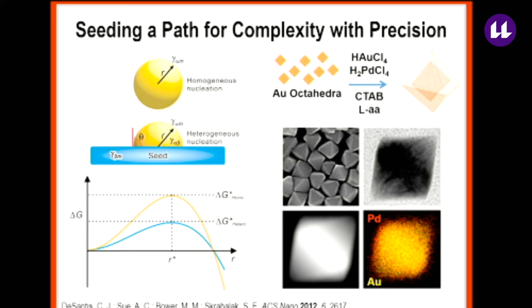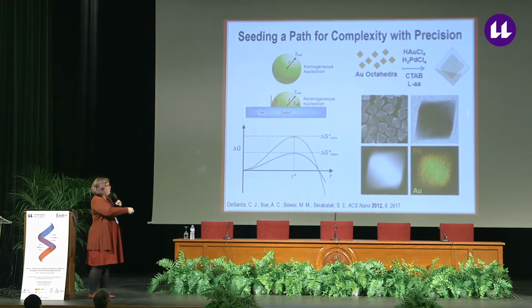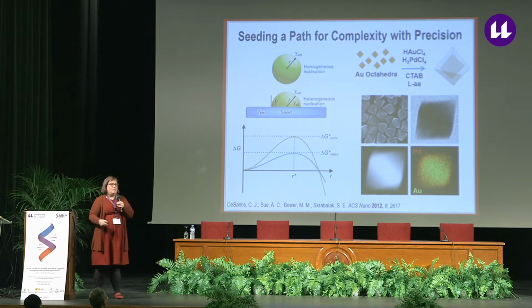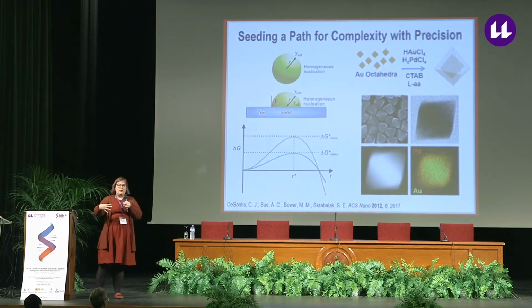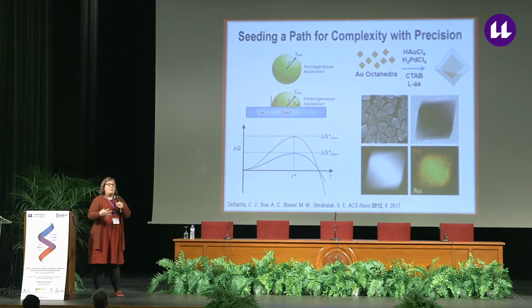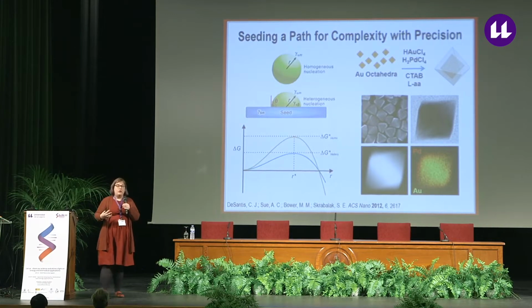And so shown here is characterization from this synthesis, and indeed we end up with octahedral-shaped nanocrystals from this seed-mediated co-reduction approach. On the bottom is STEM EDS, or elemental mapping, where the yellow corresponds to gold and the red corresponds to palladium. And you can see that there's mixing of gold and palladium up to the surface. There's an enrichment of palladium at the surface, but from powder diffraction, we were able to confirm that we did have an alloyed composition in addition to the all-gold phase from our seed present in these nanocrystals.